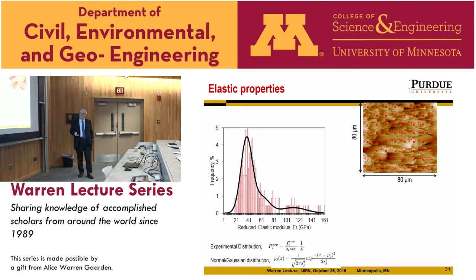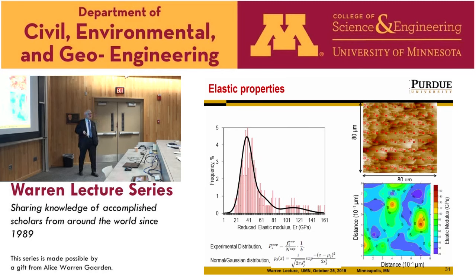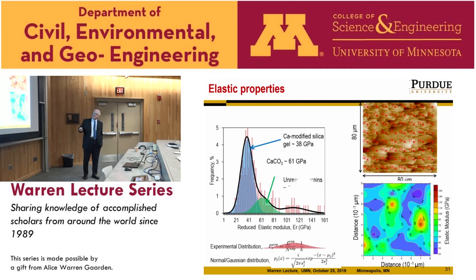So we were able to use some well-established theories for deconvoluting the values obtained from the nano indentation on all those points, and we created essentially a map of distribution of the elastic modulus. In other words, we were able to associate a given phase that formed with the given value of mechanical properties. So, for example, calcium-modified silica gel had the highest value of modulus. Calcium carbonate itself was lower, unreacted grains were lower.